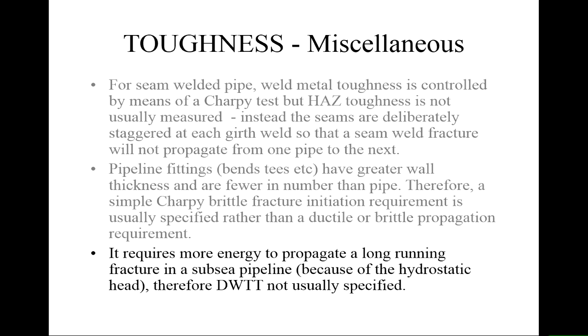So a long-running fracture in a subsea pipeline is very unlikely to happen because the hydrostatic pressure from around is actually acting to close up the cracks. And therefore we don't tend to worry so much about toughness for the subsea pipe materials, which seems a bit strange, but actually that's one case where the external conditions are working in our favour. So again, you want to check on the basic material properties, use a Charpy test, but we don't tend to specify drop weight tear tests and things like that because that's not an issue that has come up.